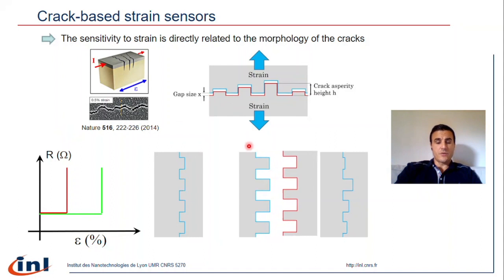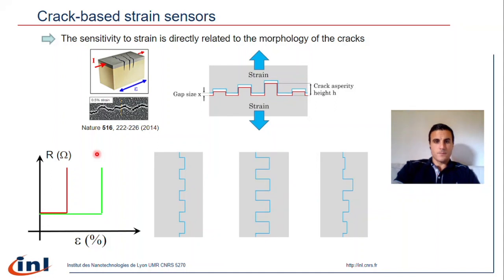Now if you consider another ideal case, another crack with no dispersion on the size of the grains, but with bigger grains. In this case, the sensitivity curve would look much more like this. The curve is shifted to the right, the contact is lost at a higher strain level. And finally, if you consider a more realistic case, with a crack showing a dispersion on the morphology, in this case, the sensitivity curve would look like this.